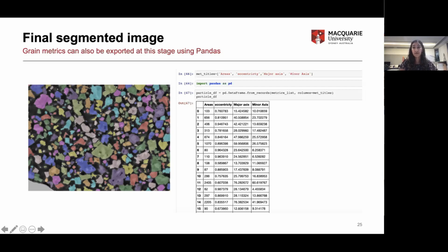So at this point, we can now assign our pixels a real size because we've removed that scale bar from the image initially. And for most SEM images, there's always metadata associated with that image. And within there, you'll find the metrics that you need to associate the pixel with its actual size. And that's also true of optical images as well.